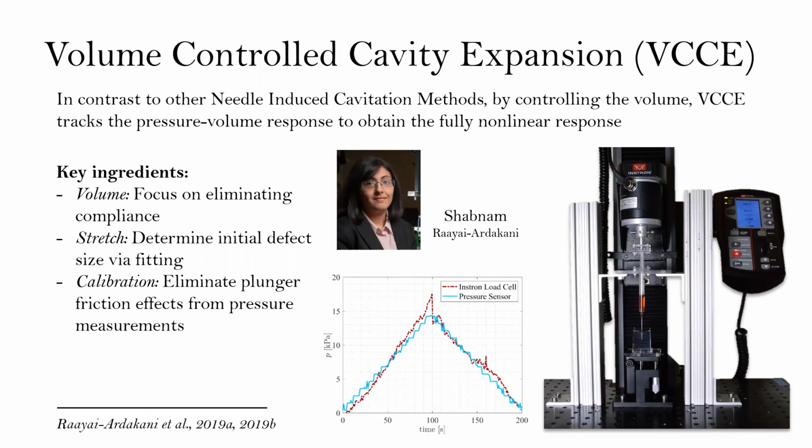to handle. Well, the first thing was we needed to eliminate any compliance in the system so that we can fully control the volume. This was not trivial to do. We ended up mounting the syringe system on an Instron, which gives us very high control, and making sure everything is very stiff compared to the stiffness of the material that we're probing. But in doing this and removing all of the different tubing and things that would have been in a different, more complicated system,